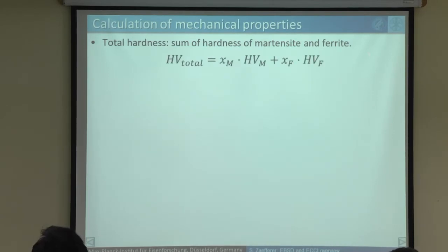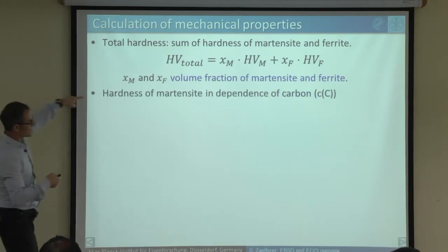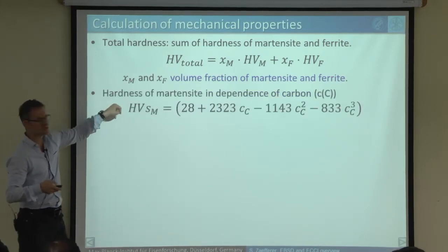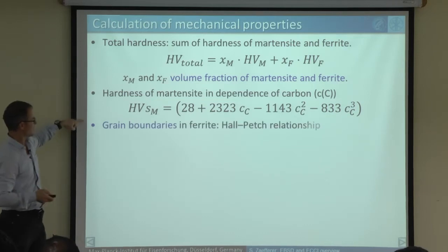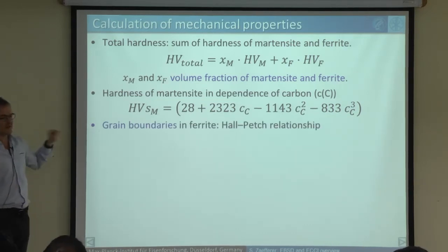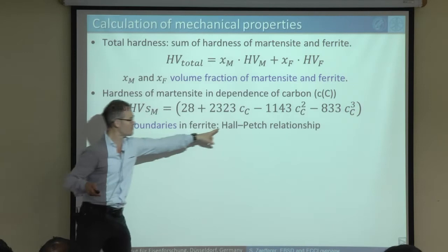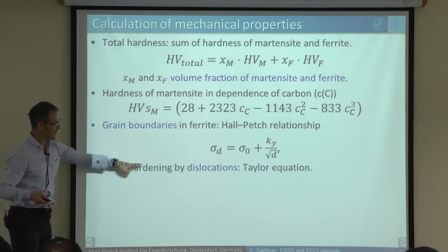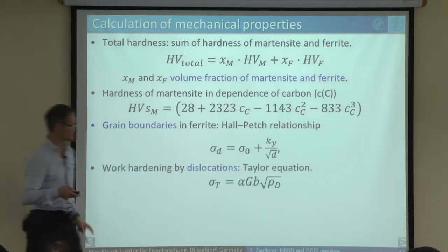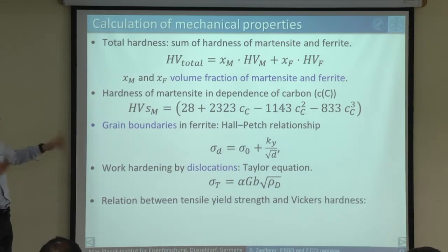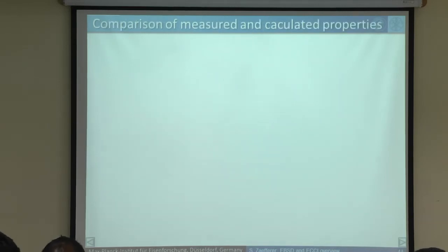So you say the hardness calculates out of hardness of martensite and ferrite, and the hardness of martensite depends on the carbon content. You can also calculate the carbon content, and then we consider the effect of grain boundaries by using a Hall-Petch relationship. We consider the dislocation density by using a Taylor equation, and finally we are bringing this all together, and we get an explanation for the strength of the phases of the material. We bring this all together in a big calculation scheme, and then we calculate.